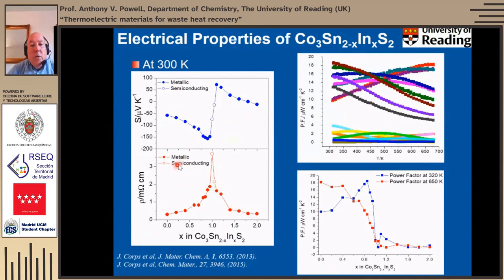So this is quite an unusual example of a metal to semiconductor to metal double transition as a result of chemical compositional changes. When we get to that second metallic region, the Seebeck coefficient never really recovers. It doesn't get the values that we get before that halfway point, and as a result, the power factors beyond that 50-50 composition tend to be quite miserable compared to those before that 50-50, and we can see that graphically here at 2 temperatures. It sort of falls off a cliff edge as we get to that 50-50 composition.